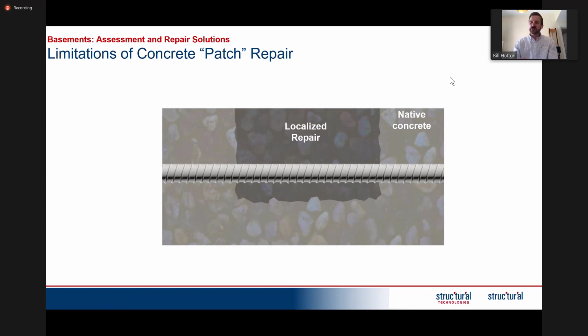So we assume that this concrete repair was required because the concrete became contaminated with chlorides or carbon dioxide or carbonation. So we removed all of the damaged concrete, we cleaned the steel, we added steel, we cast it back, we did a pull-off test, everything's okay. This steel now is good for, say, 10 years. In the area you've repaired, you should face no problems.